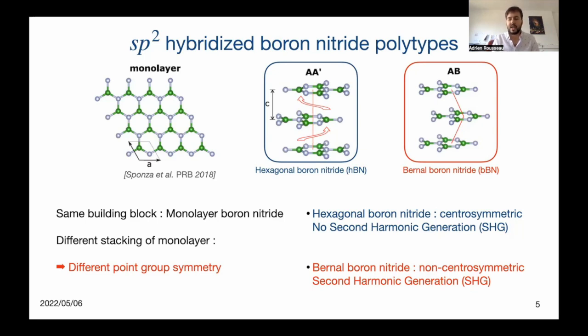Another polytype is the Bernal boron nitride, which consists of alternatively shifted layers by 1/2 of the in-plane lattice parameter, where half of the atoms of a layer are at the center of the hexagon of the next layer, namely the AB stacking. Because of their different stacking, the polytypes present different point groups, which induce different properties.